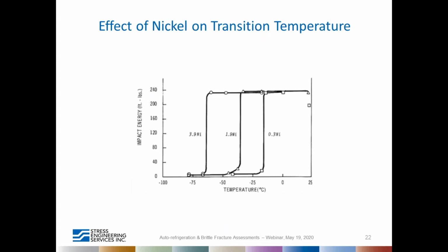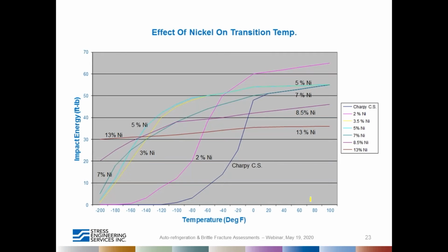Let's look at the effect of nickel on the transition temperature. We know that the nil ductility temperature is somewhere here, and you can see that the addition of nickel certainly helps in reducing that nil ductility temperature as we go higher in nickel. So this is a colorful edition of the previous slide with more materials, and you can notice that the stainless steels do not exhibit this nil ductility temperature transition.